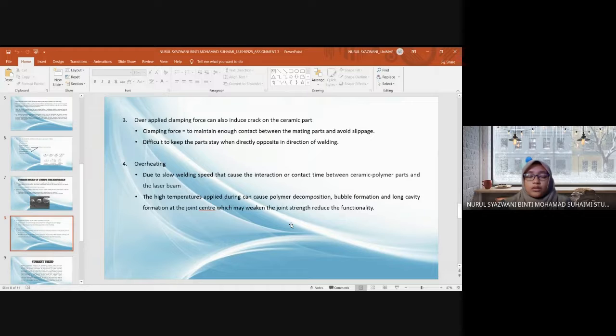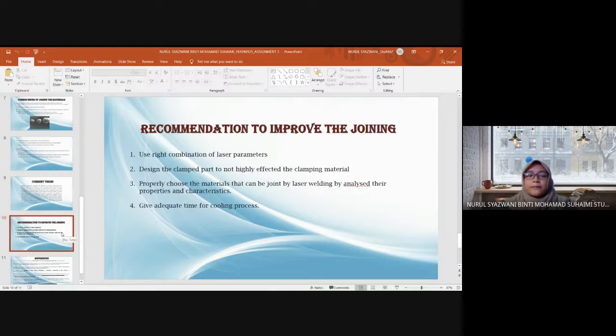The fourth one, or the last one, is overheating. It is related to slow welding speed that causes the interaction or contact time between the ceramic polymer parts and the laser beam to become longer. So the high temperature applied during this process can cause polymer decomposition, bubble formation and long cavity formation at the joint center, which can weaken the joint that has just occurred.